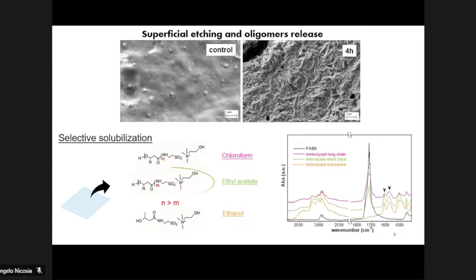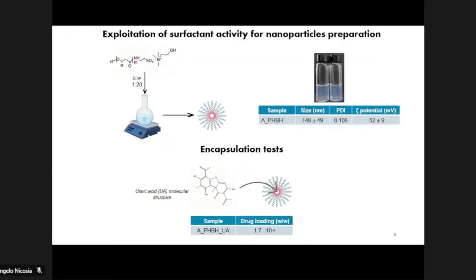The second fraction resulted to be the more interesting, as it could have amphiphilic properties and could be used as a surfactant. For this reason, it was used for the preparation of an oil and water emulsion, which allowed us to obtain nanoparticles. Since these nanoparticles could be useful for hydrophobic drug delivery, encapsulation tests were carried out using a model molecule.